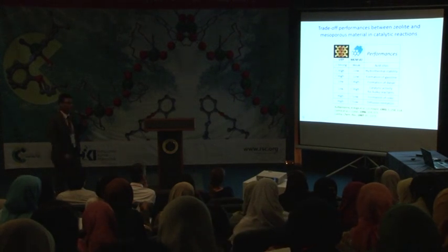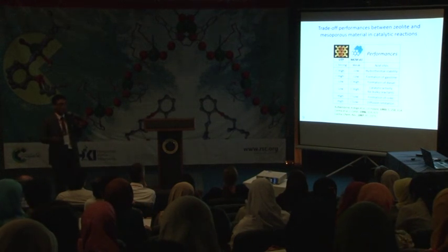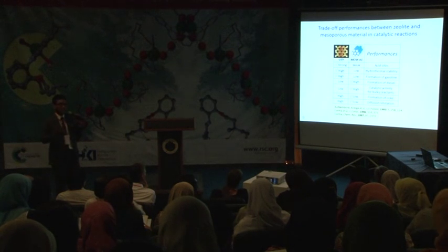Zeolite is a micropore material, but of course to carry out this industrial catalytic reaction, we need other than micropores. So that's why we also involve the matrix, so it contributes the mesoporosity in this process. But in fact, the zeolite could not contribute up to this far. So actually, this is the motivation for us to synthesize zeolite with hierarchical porosity, containing extra porosity, such as mesoporosity or probably macroporosity.